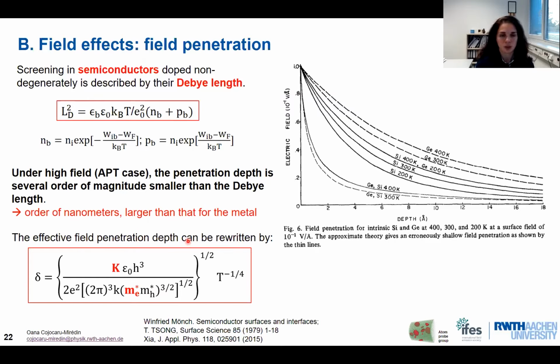So in this equation, it's nicely shown that the effective field penetration depth is directly proportional to the dielectric constant and inversely proportional to the effective mass of the electrons. The dielectric constant is a very important parameter, and we know that it can vary a lot within semiconductor or insulator materials. For example, narrow bandgap materials used for memory applications, like phase change materials, have dielectric constants which are 2 or 3 orders of magnitude higher than standard semiconductor material like silicon. So of course, a much higher dielectric constant means also a much higher penetration depth. And I will show you at the end of this lecture how this can have an implication in terms of physics or in terms of bond breaking within the atom probe measurements.